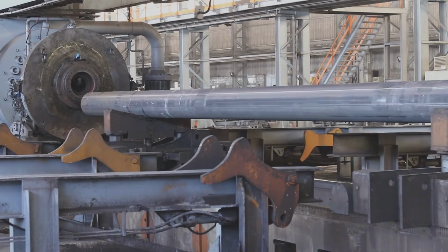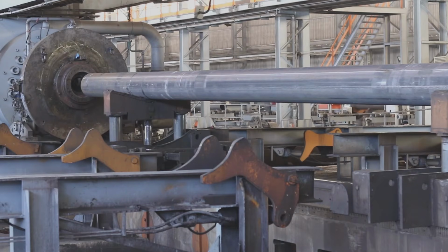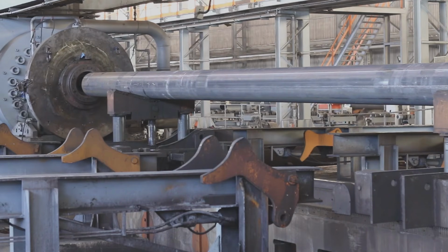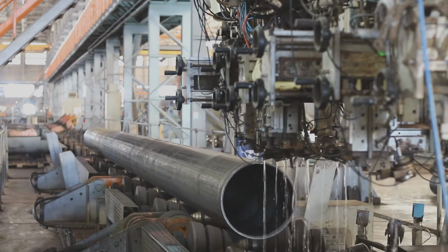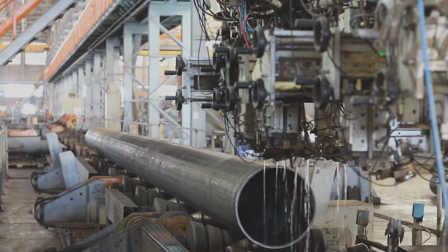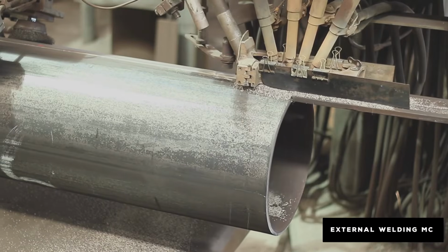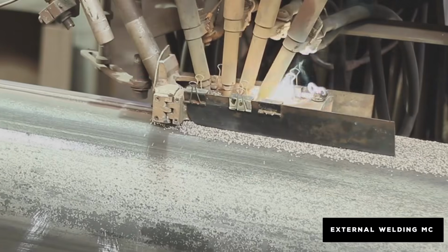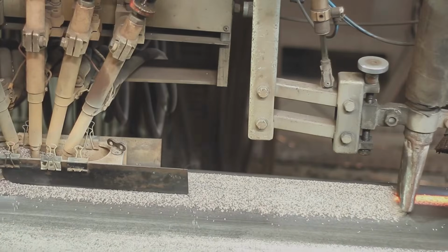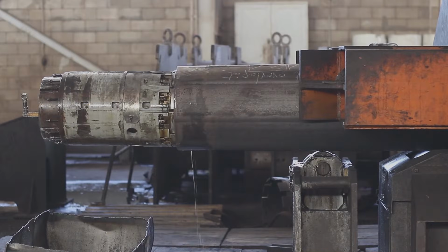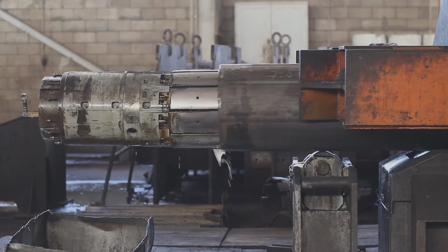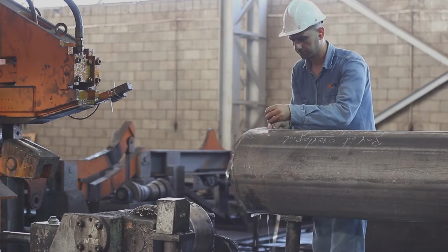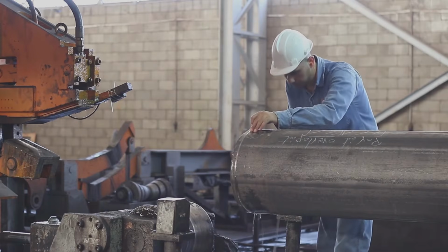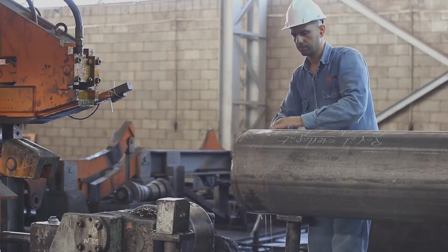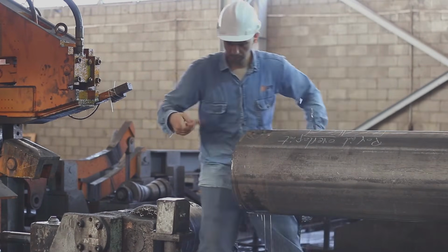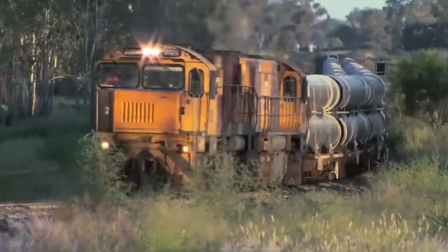The flat sheet curves slightly at the edges. Then more rollers press in, increasing the curvature until the steel begins to resemble an open pipe. By the time it reaches the final stage, the edges are aligned so precisely they appear almost fused together. But this is where the pressure builds, because alignment here is everything. If those edges don't meet perfectly, the weld that follows will carry hidden stress, and that stress doesn't show up immediately. It shows up later, under pressure, when the pipeline is already in use.